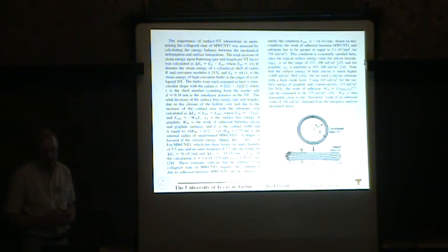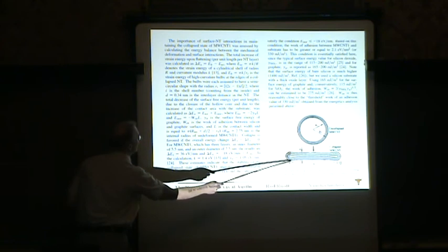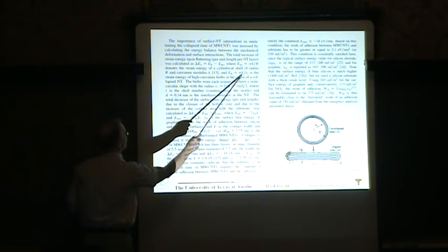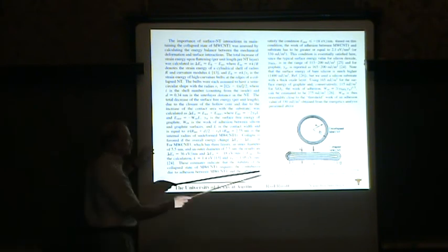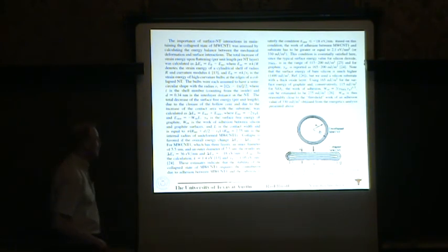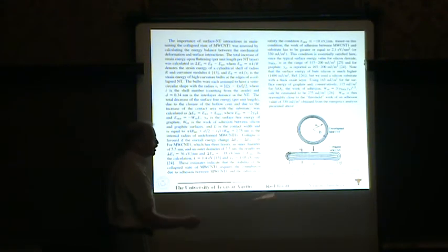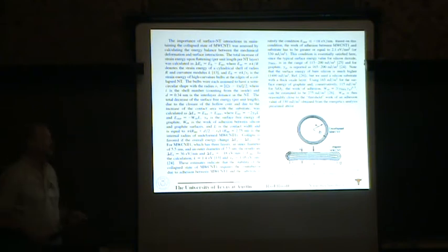And so the surface energetics that we worked out here, this is a lot of reading, but I've just told you to calculate that bulk is this statement here, 5 times the stiffness divided by radius of curvature. And then we have this adhesion that I told you about here. And we calculated for this particular three-wall tube that it actually was not stable to collapse without the adhesion to the SiO2.